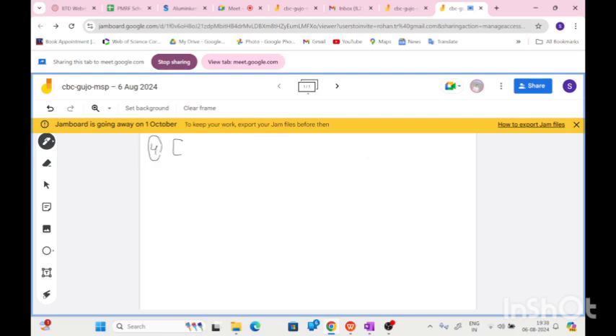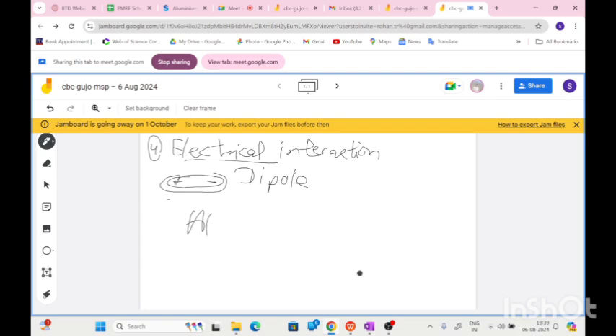Fourth is the electrical interaction. In electrical interaction, we know a dipole forms. In an atom also, due to thermal or atomic vibration, the positive and negative charge can accumulate at a site, which results in a dipole. So if this element goes into the aluminum matrix, it will impose an electrical interaction with the aluminum atoms, and because of the different volumes, they lead to the strengthening of the aluminum alloy.